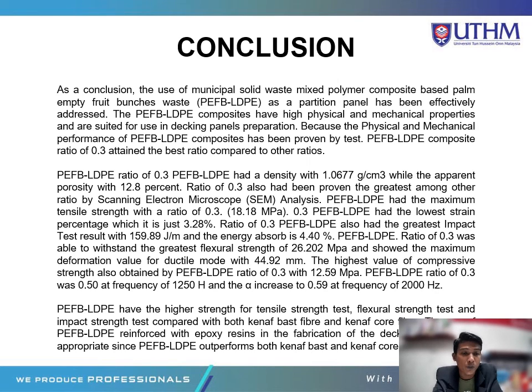PEFB LDPE ratio 0.3 had a density of 1.0677 while the apparent porosity was 12.8%. Ratio 0.3 also had been proven the greatest among other ratios by SEM analysis. PEFB LDPE had the maximum tensile strength with ratio 0.3, which is 18.18 MPa. 0.3 PEFB had the lowest strain percentage, which is just 3.28%. Ratio 0.3 PEFB LDPE also had the greatest impact test result with 159.89 and the energy absorbed is 4.4%.